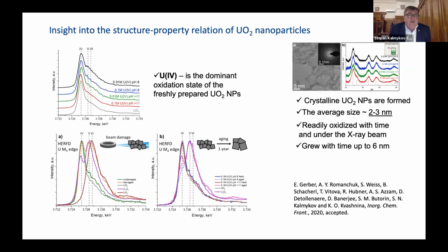I don't have a lot of time, but I still have several examples to show. Just one slide concerning uranium. For uranium dioxide particles, the behavior is much more complicated compared with thorium. This is not very surprising, because of the stability area in the Pourbaix diagram. Under neutral pH conditions, uranium-4 is dominating. This is the major redox state, compared with uranium, where we have both uranium-6 and uranium-4, and certainly uranium-5 could be present. So there are many more possibilities for redox mixtures and redox changes in the particles.